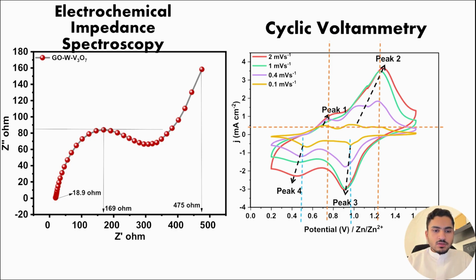Next is the electrochemical impedance spectroscopy and cyclic voltammetry. On the left is the electrochemical impedance spectroscopy, where we have the solution resistance at 18.9 ohm and the charge transfer resistance at 169 ohm and the Warburg impedance at 475 ohm. For the cyclic voltammetry, it shows the redox nature in the battery, where we have the upper peaks in the plot for oxidation in the anode and the lower peaks in the plot for the reduction in the cathode. It also shows the potential and current of those peaks.